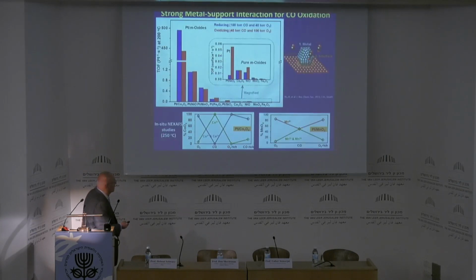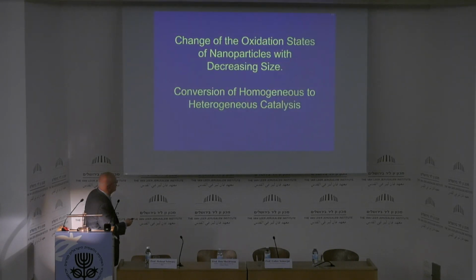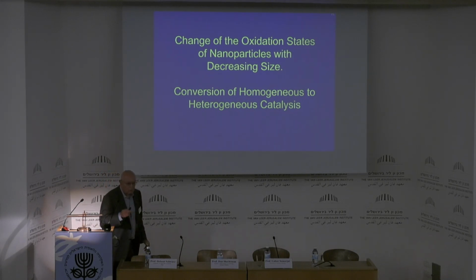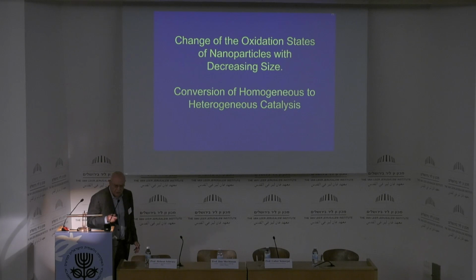Now, there are very interesting situations when you look at the cobalt oxide platinum interface, because you get CO oxidation rate 7,000-fold more than when you take any other platinum, other oxide interfaces, and I can explain it to you. It's a very interesting chemistry. Now, now comes the discovery mode of how to combine the 3 fields of catalysis: enzyme, heterogeneous, and homogeneous.